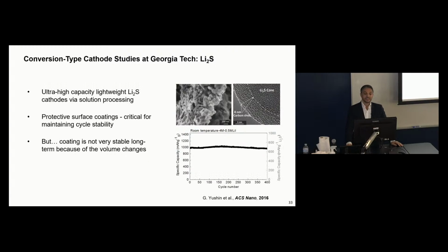And so if you make, let's say, these lithium sulfide particles, as I mentioned, during some point of charge and discharge, they tend to form polysulfides, long-chain polysulfides that dissolve into the electrolyte. So how do you overcome this challenge? If you use lithium sulfide, it has a very high melting point, very good thermal stability. You can heat it up to, let's say, 800 C. And then if you have the thermal stability, you can deposit all sorts of coatings on the surface of the particles that would prevent direct contact between electrolyte and active material. And so that's what we did some time ago.